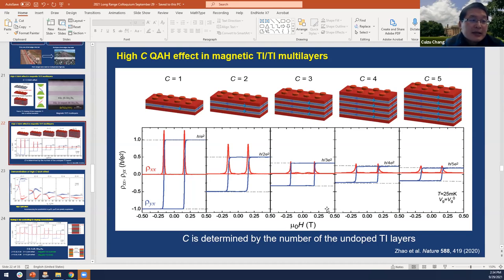In my opinion, the longitudinal resistance becomes larger as you increase the thickness just because of the growth and because of the synthesis. And now after we published this paper, we greatly improved the growth recipe. Now I can say we can grow C equals 10 quantum anomalous Hall layers.